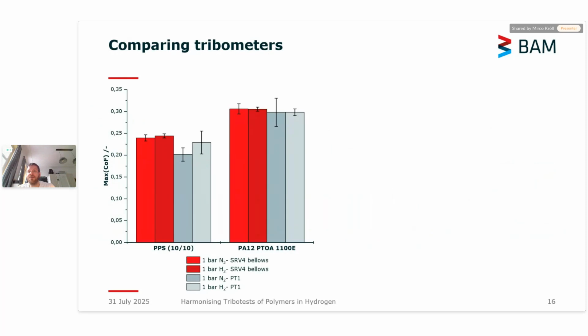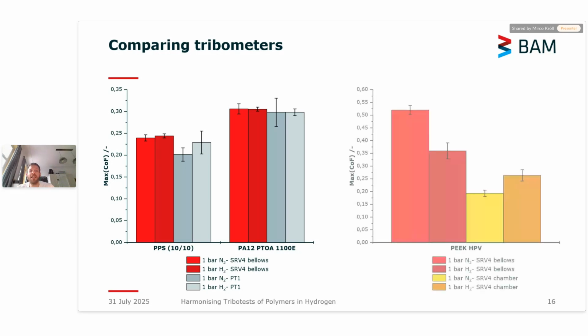When you want to compare tribometers, I need to hurry now a little bit. We are seeing here on the left-hand side the comparison between the SRV4 with the bellows in Austria and the PT1 at BAM. The friction is rather close, so I would say, well, it's just one data point, but it's safe to say that at least at that data point, both tribometers deliver comparable maximum coefficients of friction. If you do the same thing for the two SRV4 type tribometers, the one in Austria and the one with the chamber at BAM in Berlin, you can see here that even the trends are different. So something is not comparable here.